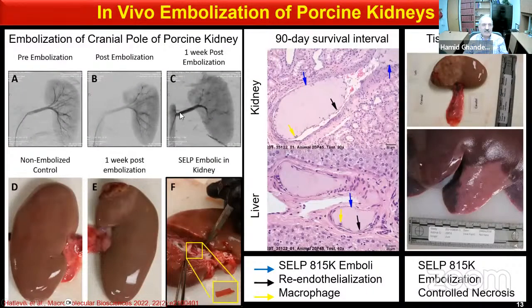The next thing we did, this work we did with a contract research organization in porcine kidney, to demonstrate the embolization of the cranial pole of the porcine kidney. What you see on the top left, or maybe it's your top right, is basically pre-embolization. You can clearly see the vascularity, post-embolization, and after 1 week post-embolization, you can see that the tissues are basically dying, causing tissue necrosis as a result of this embolization, and you don't see blood flowing through those. This is also true in the figures down here, where you have non-embolized control, 1 week post-embolization, and we could actually isolate the silk elastin block copolymers that have formed hydrogels in this kidney.